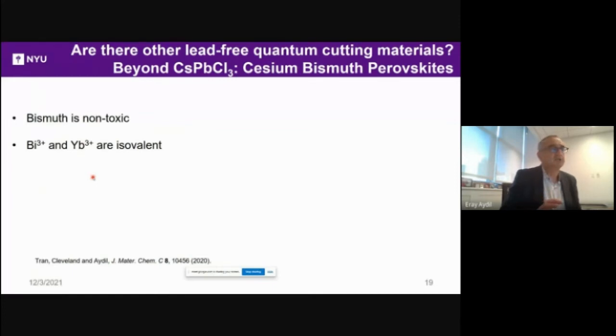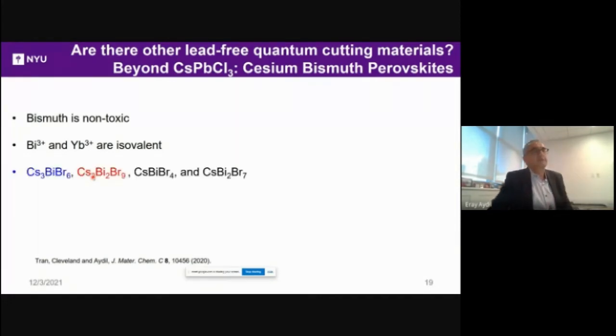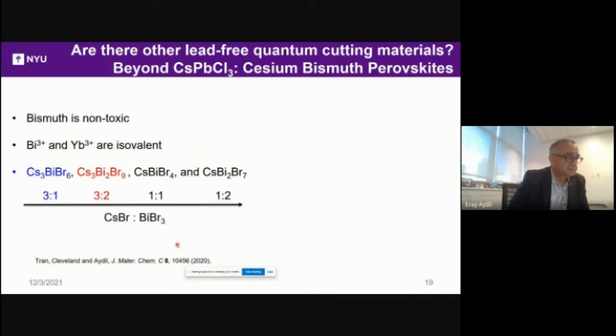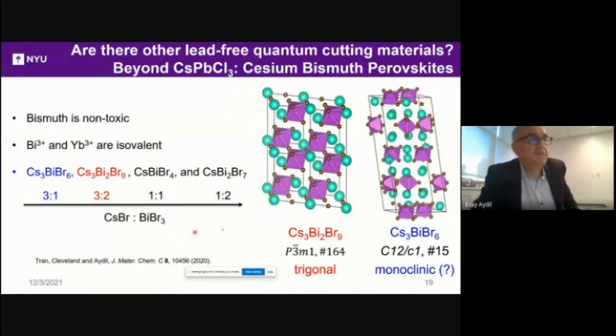One thing is that bismuth 3+ and ytterbium 3+ are isovalent. So one can get around the limitation of putting a limited number of ytterbium 3+ into the material, limited to 1 to 8% because lead 2+ and ytterbium 3+ are not isovalent. And if you look at what you can make with cesium and bismuth, there's a host of compounds of different stoichiometry. We actually looked at a number of them. I'm going to focus on just a couple here. You can control it by changing the ratio of cesium bromide and bismuth bromide, which are the precursors for making these bismuth perovskites.